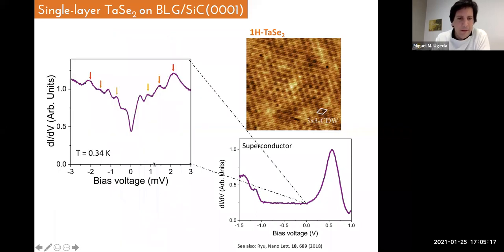And if you look at the superconducting gap, you can still see it surrounded in general by the spin excitations. Anyway, I have to admit that the visualization of these peaks in general is much harder than in niobium diselenide. And one of the reasons is because the critical temperature in this material is much lower than in niobium diselenide, probably 1.3 instead of 2, which is not a big deal. I mean, it's not a big difference, except if you are considering that we are working at 300 millikelvin. So that difference makes a big difference for us. And that's why the conductance in the superconducting gap doesn't go to zero here. And we are in a situation where seeing these features is tougher than in the niobium diselenide.